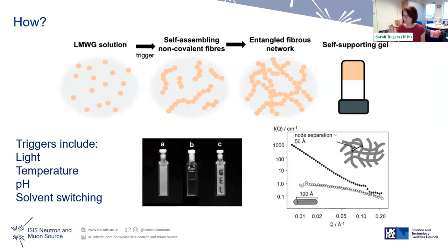We basically had the sample, we made a little mask for it with the word gel on it, we shone a light on it, and you can see clearly where the gel mask was. Some of it has gelled and some of it hasn't. And that's the scattering profile that you see before and after gelling. So the white dots are just the normal, the molecules on their own. And then when we gel them, they form this network. And we can even see the node separation, which is that little bump that you see in the data. So we get quite a lot of information on the before and afters of these samples.